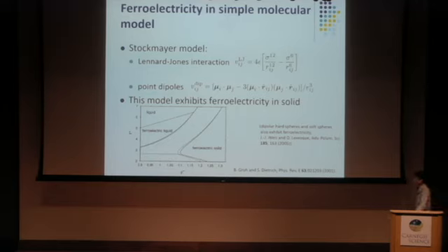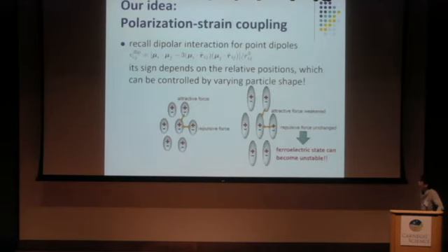So for the point dipole model, this was developed in liquid theory. This is called the Stockmayer model, having the pair Lennard-Jones interaction and the point dipole electrostatic interaction. And this model is known to exhibit ferroelectricity in the solid phase in this paper. But please recall that the dipole interaction for point dipoles is highly anisotropic. By anisotropic, I mean its sign depends on the relative positions, which can be controlled by varying particle shape, as